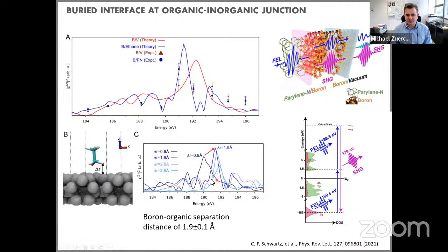And one thing one can do in these kinds of measurements is simulate for different interfacial spacings, like what is the bond length from boron to this organic at the interface? If you bring it closer together, the simulations predict that the spectrum shifts even to lower energies, whereas it shifts to higher energies if the bond is elongated. So in other words, you get a way to intrinsically measure these interfacial bond geometries without cutting it apart. You can measure those in situ, and maybe in the future even dynamically, when you think about charge transfers and photoexcitation events and things like that.